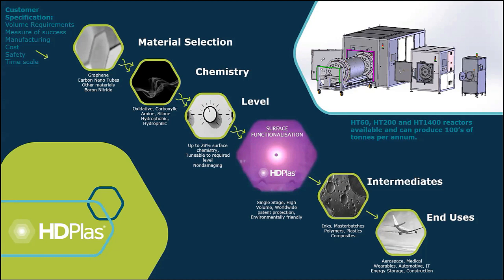We can then choose the chemistry: oxidative, carboxylic, amines, silanes, hydrophobic, hydrophilic, depending on the need. We can tune the level of chemistry. That's key because too much functionality can alter the formulation or mask the properties of graphene that you're trying to provide. They go in our plasma reactors. It's a single stage, high volume, worldwide patent protected, environmentally friendly process, but we don't stop there. We take the powders and we can put them into an intermediate. We've got our own manufacturing facility here in the UK for that.